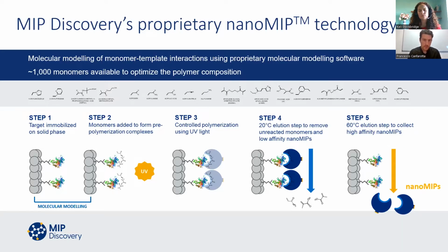In the section in the center, you can see how monomers look. Well, some of them at least, and all of them have 2 main moieties always in common. A polymerizable part, which is given by a double bond in this case, and another moiety, which is the portion of the monomer interacting with the template molecule. The kind of interactions, of course, will depend on the monomers, the solvent, and the template itself. They can range from hydrogen bonding to hydrophobic interactions, electrostatic interactions, or dipole-dipole interactions.